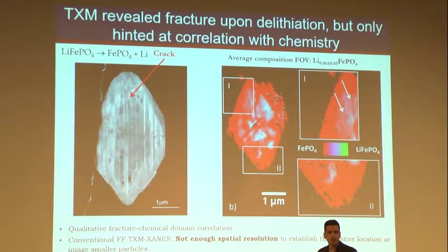The image on the left is showing you what happens morphologically to the particle, and it's fracturing. It's formed these very striking fracture lines. The image on the right is the TXM image, where we did it with a hard X-ray microscope at the iron K edge. And so we reconstructed the spectra with standards, and we were able to assign where the iron 2 was and where the iron 3 is. If you look, you're going to see that there's most of the iron 3 on the outer rims of the particle, but you start seeing features, if you zoom in, that run down that are very reminiscent of those fracture points. The problem is that the spatial resolution wasn't enough to know if crack and red line were exactly on top of each other or adjacent to each other.